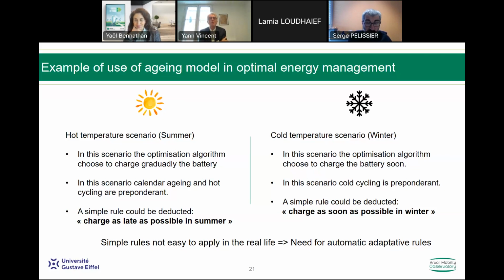This is in summer. But you won't do it in winter, because in winter, if you charge as late as possible, it means that the vehicles will arrive in the evening and keep the battery uncharged all the night. The temperature of the battery will decrease. And when you start the charging at 2 o'clock in the morning, the battery may be at a temperature of maybe 10 or 5 or even -2 or -5.